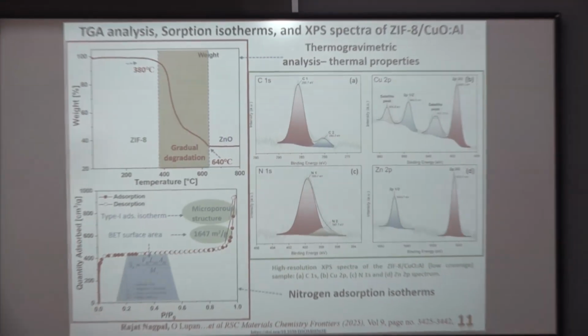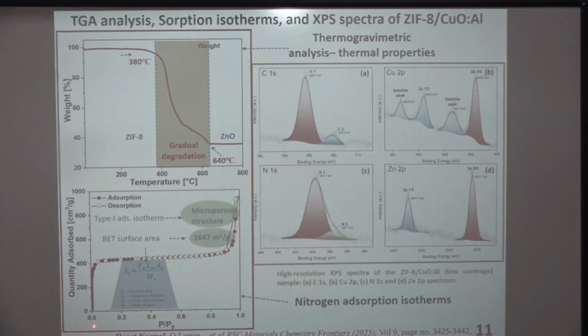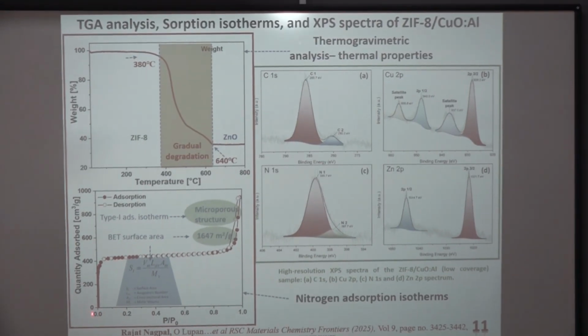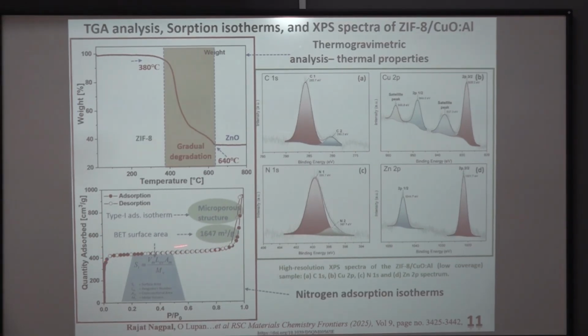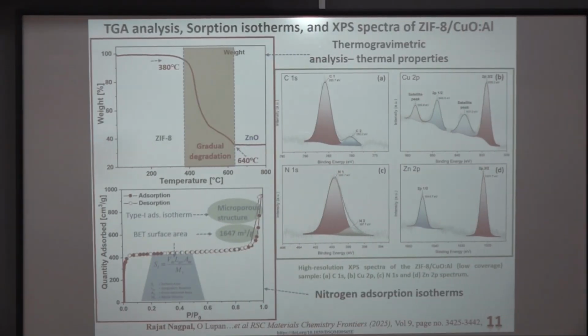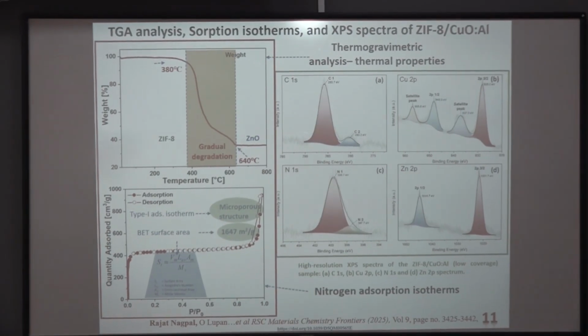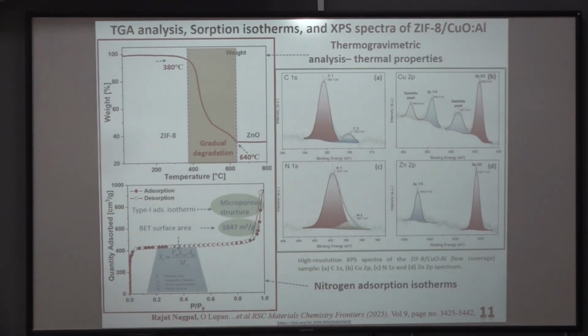And now to get insights about the adsorption isotherm, here we can see even at very low nitrogen pressures, there is a quick nitrogen uptake and then a stable plateau, which confirms it as a type 1 adsorption isotherm, which is associated with the microporous structure. And using this BET equation, we calculated the BET surface area.